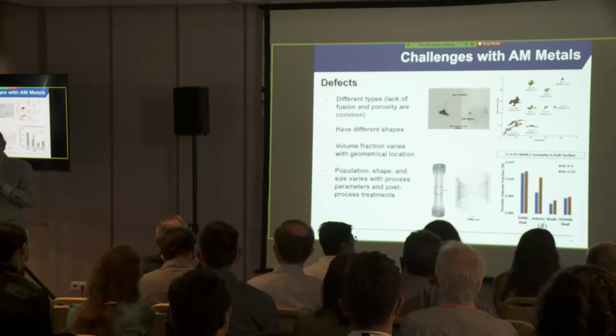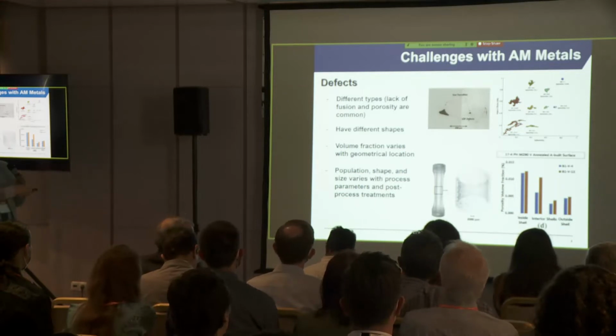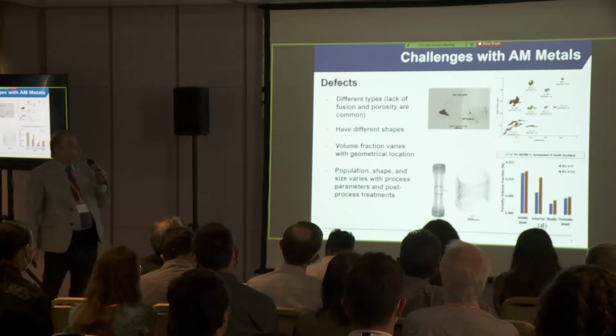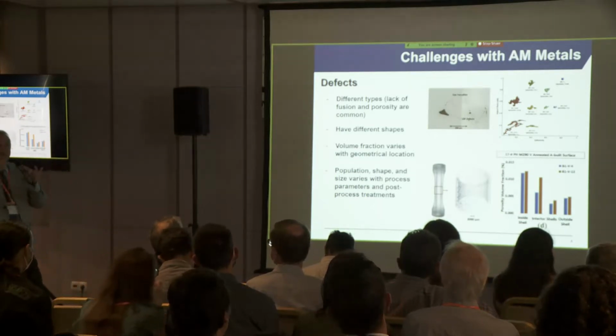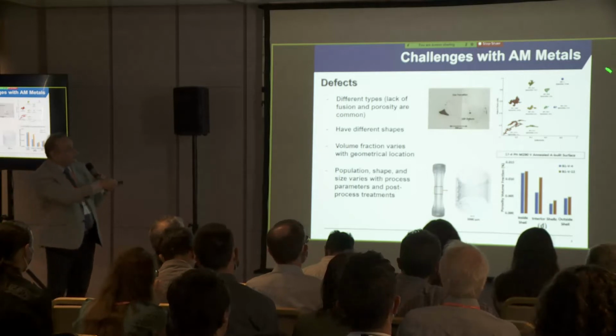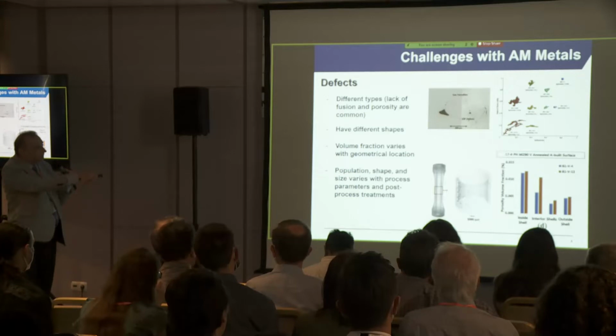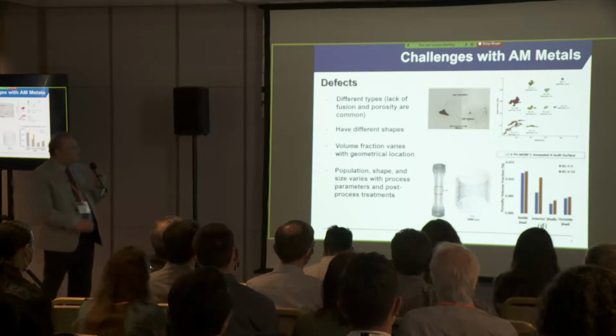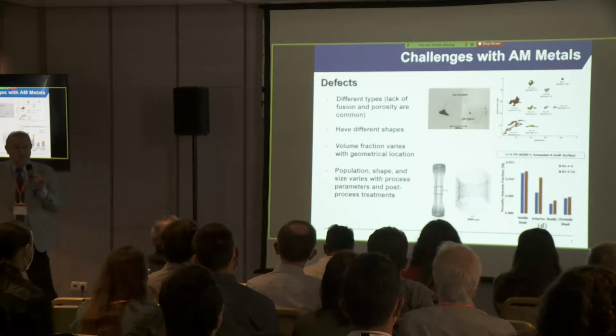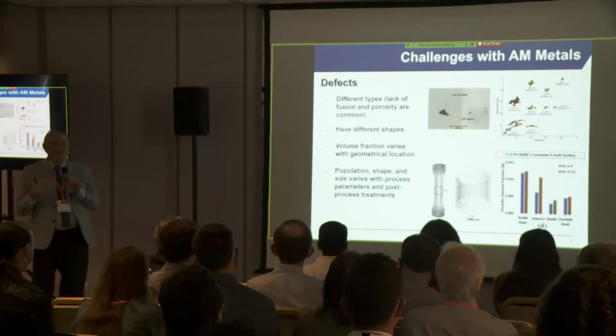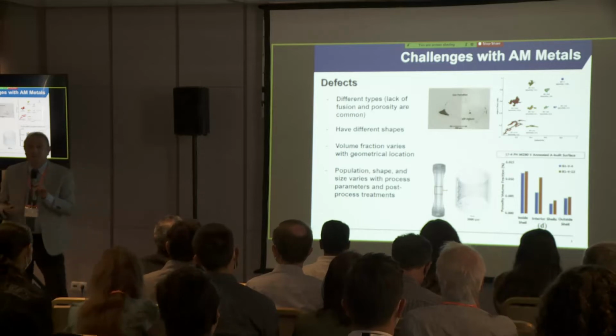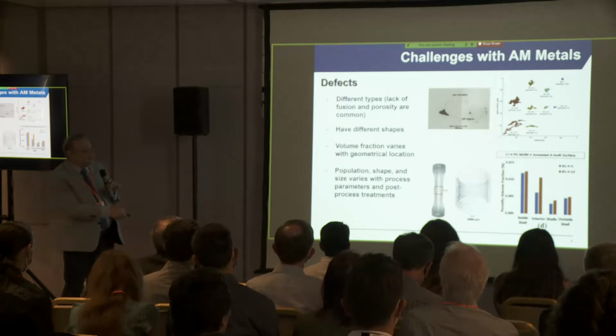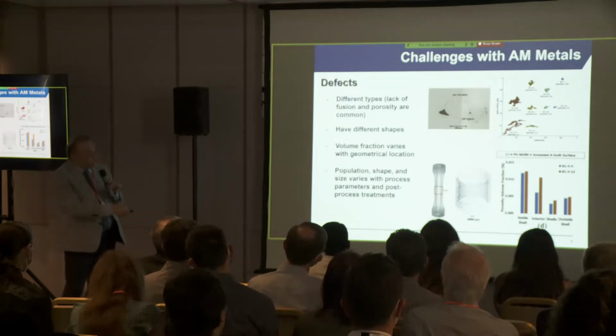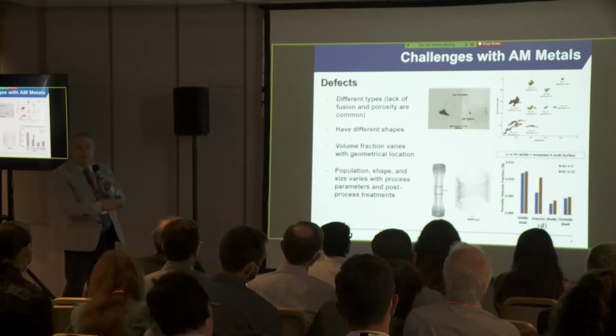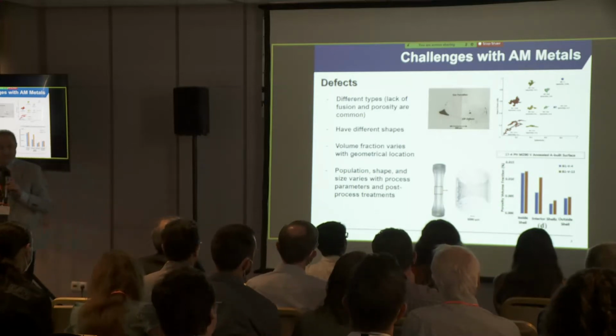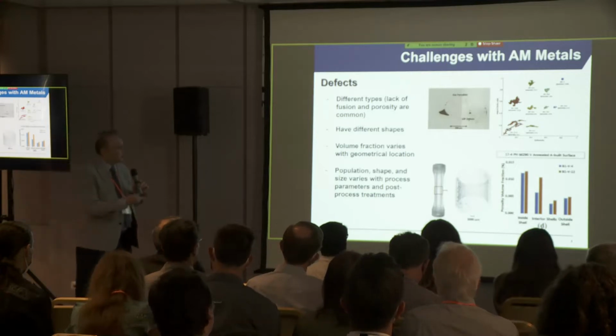Okay, so one big challenge is defects, typically lack of fusion defects and porosity. These defects of various sizes and shapes, you can see an overview of the type of defects on the right slide. And a volume fraction of defects varies throughout the geometry. So the fact that there are defects is a challenge, but a bigger challenge is the variability. So even if you think about a thin wall tube, when you make a thin wall tubular specimen, the defects, their volume fraction changes quite a bit over a 2 millimeter thickness. So the variability is the main issue in dealing with defects.